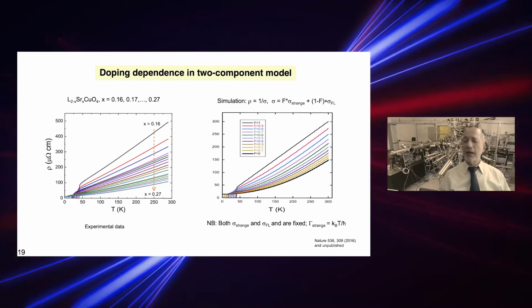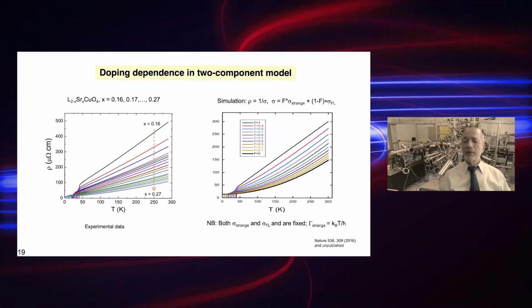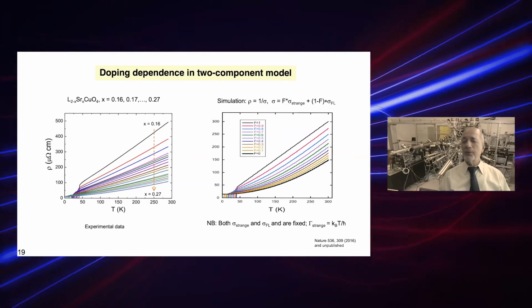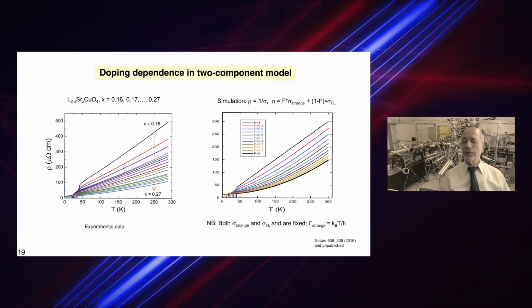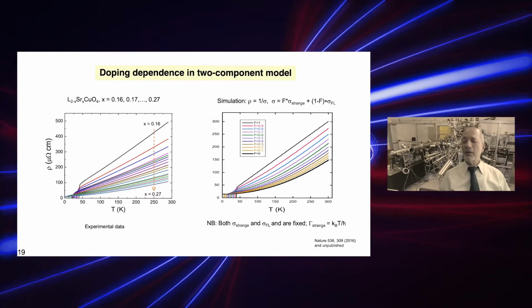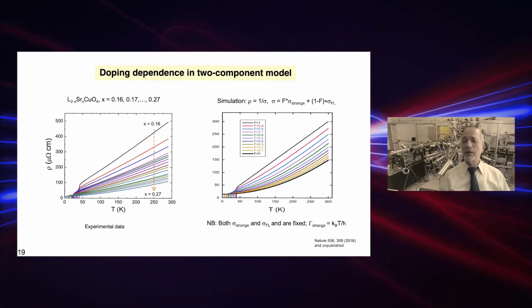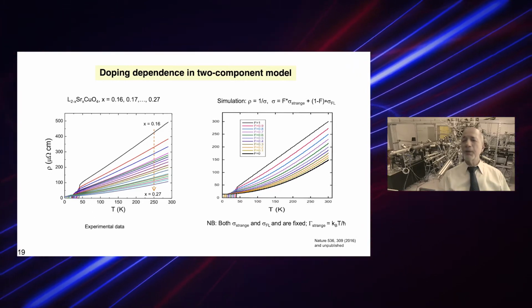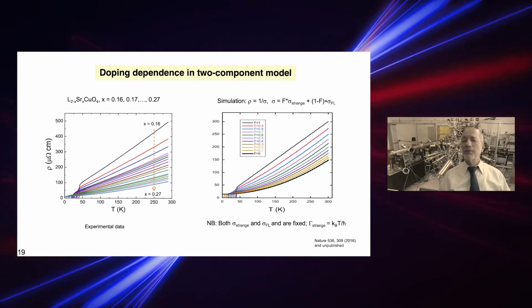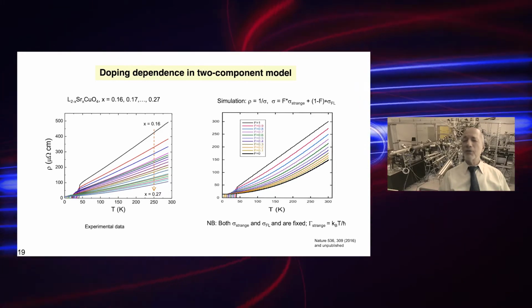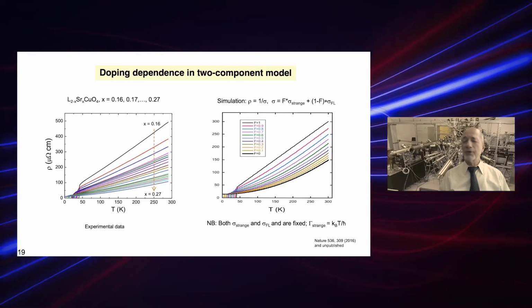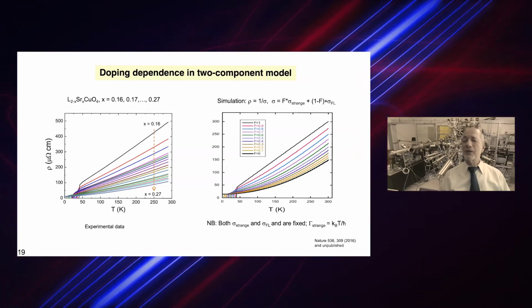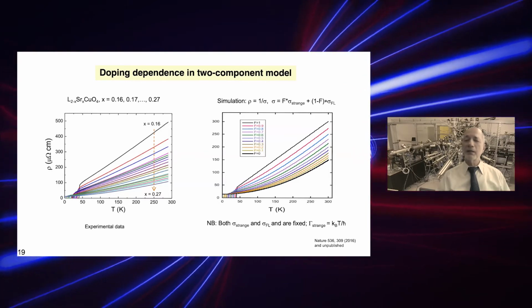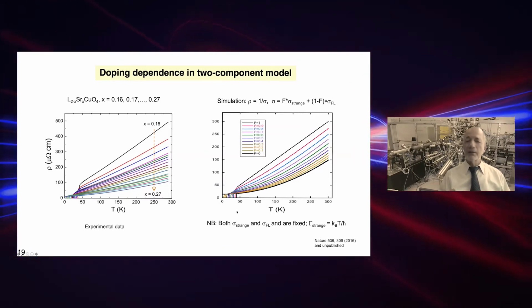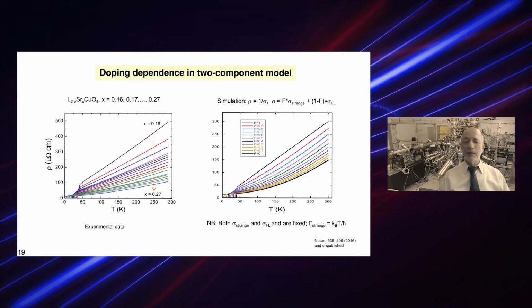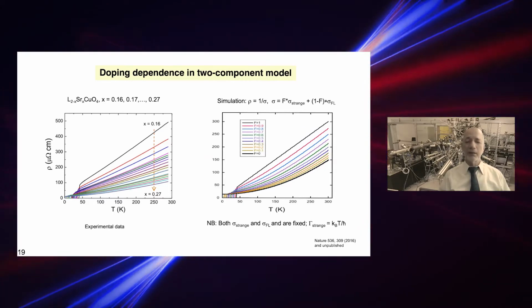So what I have done here is I have fixed the strange and the Fermi liquid components. The strange metal component is fixed to have the Planckian scattering rate, which is k_B T divided by h. What I'm varying as a function of doping is their relative contribution. So the strange component is decreasing from 1 down to 0 at the dome edge, while the Fermi liquid component is increasing. And nothing else. You can see that there is striking similarity between the data and the simulation.